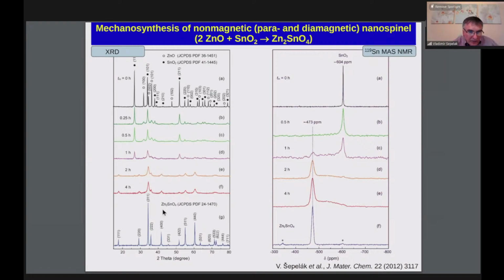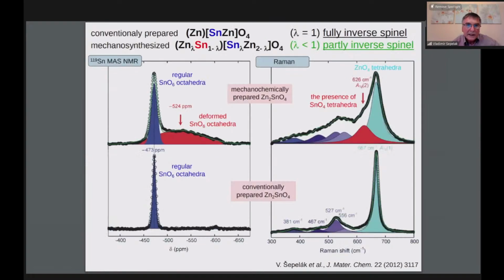and tin dioxide. And here is a comparison of these diffraction patterns. Here is the bulk material reference sample, and here in the red line is the mechanosynthesized material. The same for the NMR spectrum, and you see that we have an additional subspectrum here. If we compare these two spectra, I can show you on this picture. That means we are comparing now NMR spectra of mechanosynthesized zinc stannate and